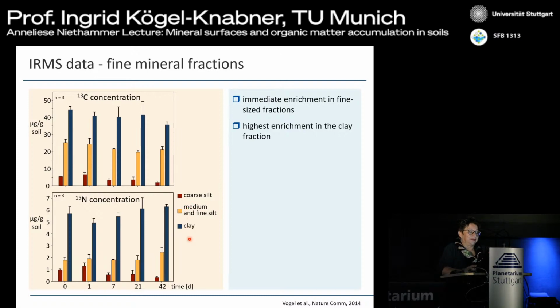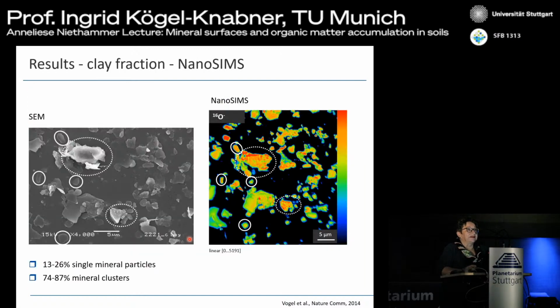When we then look at these fine fractions, we see, first of all, I hope you can see that this is scanning electron microscopy that we always do before we go to the NanoSIMS, because otherwise the NanoSIMS resolution is so high that we are lost in our sample. So we first have to get an overview, and we do this with the scanning electron microscopy. And we find a lot of clay particles. We find, first of all, that less than 26% are single mineral particles, and a lot of them are mineral clusters. So we have single particles like these here, but a lot of them are clustered, although we tried to disperse the soil and to release only primary single minerals.